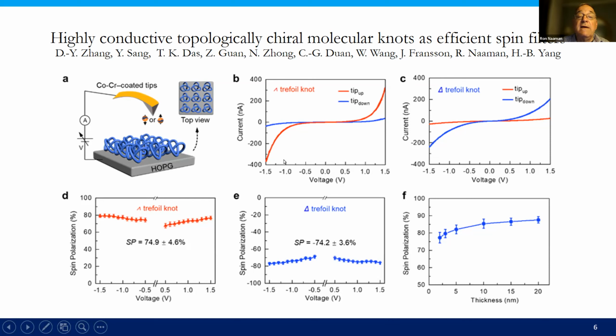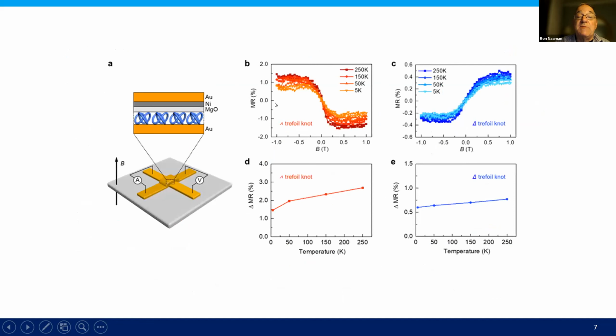Another interesting finding here is that the current we get is huge. It's about 2 orders of magnitude larger than the current we get with regular molecules that have no conjugated systems. And here is the spin polarization. We get 75% spin polarization at room temperature. But what is really interesting is that when we do the same experiment that I described before, but now we change the temperature, basically the spin polarization doesn't change much with temperature.